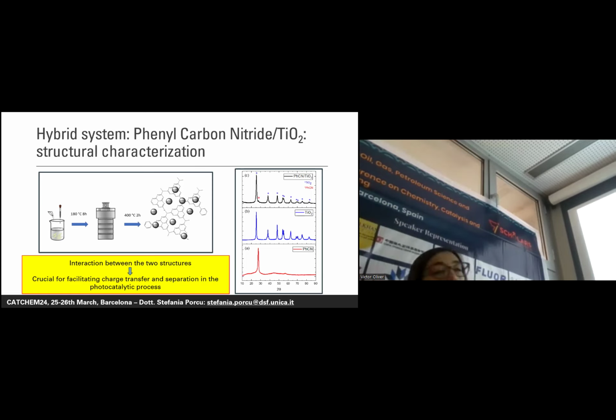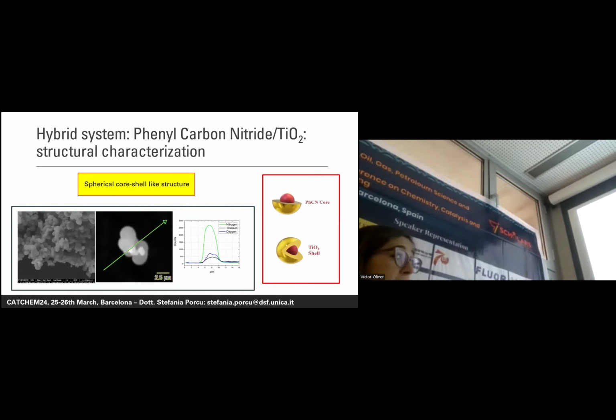Even for this material, before studying all the possible applications, we did all the structural and optical characterization. So the first thing we did was the X-ray diffraction analysis that showed us the perfect interaction between the organic and the inorganic part, because as you can see from the black graph, the one on the top, in the X-ray diffraction pattern of the hybrid material, we observe both the contribution of the organic and the inorganic part, meaning that we were able to obtain a hybrid system.